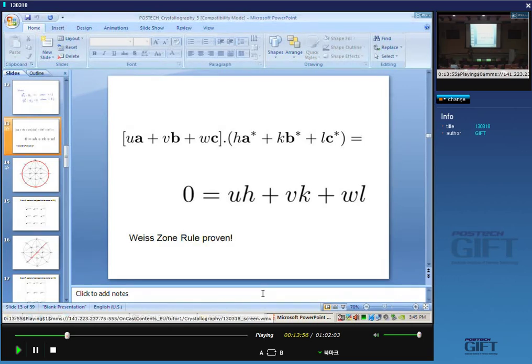non-coplanar directions, right? So this rule applies to whatever your crystal system is, whether it's monoclinic or cubic or hexagonal, whatever it is. If uh plus vk plus wl is zero, then the direction uvw lies in the plane hkl. Okay? So no need for you to do any geometry, etc. This dot product proves the Weiss zone rule directly.